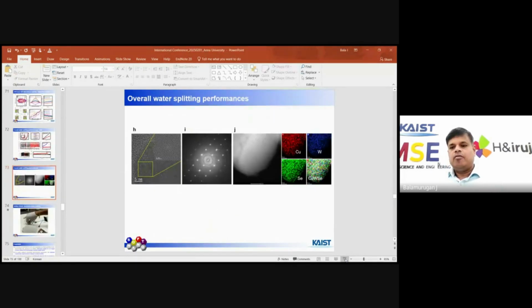We also have to prove the crystalline nature after the durability test. You can see the crystal structure is maintained. TEM and STEM analysis and FFT clearly show that the crystal pattern is maintained and the selenium is almost retained. There is not much loss during the oxygen evolution and hydrogen evolution in the bifunctional activity of OER and HER.